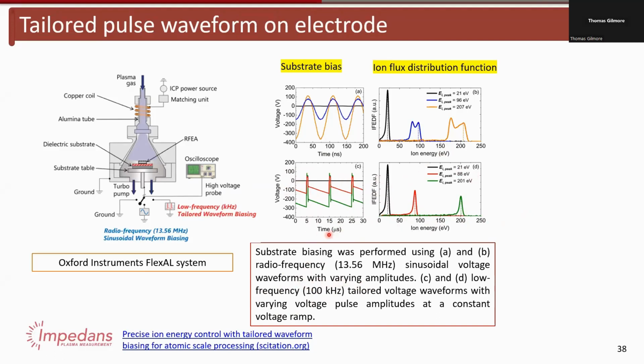The benefit of using low frequencies is you can use this to achieve much higher energies. So this is probably the way to go in the future for ion energy control, not just for high energies, but also low. You may want to produce a plasma with ions at the 3 eV, 4 eV, 5 eV mark, like if you're doing atomic layer etching or deposition. You want very fine control over the energies, so this is the way you'll need to go. I think tailored waveforms and atomic layer processes are going to go hand in hand over the next 5 to 10 years.